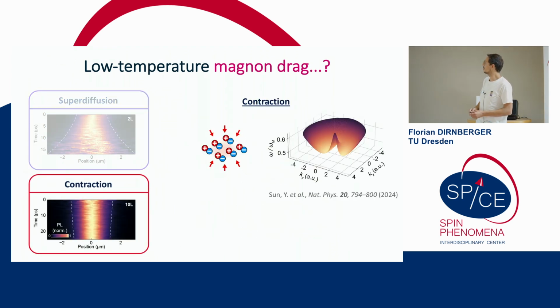The contraction is very interesting because very recently the group of Joseph Orenstein published a paper where they investigated particularly the role of dipole-dipole interactions for this material. Their conclusion was that magnons with a very small wave vector actually have a negative group velocity in this material. So we're thinking about what it means when we create magnons with a negative group velocity. That would seem to be a magnon wave where the phase front propagates outwards, but the group velocity and the momentum of that wave actually point inwards, which means that the excitons would not be scattered outwards, but actually inwards.